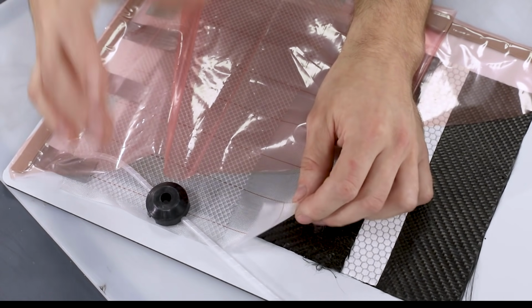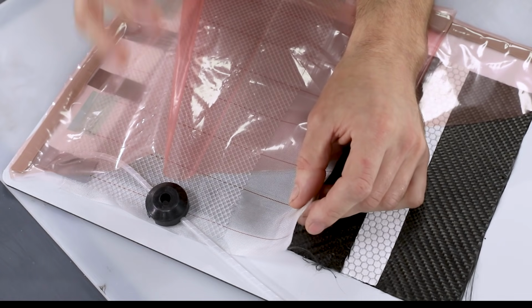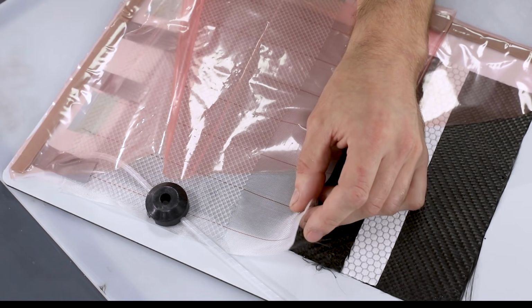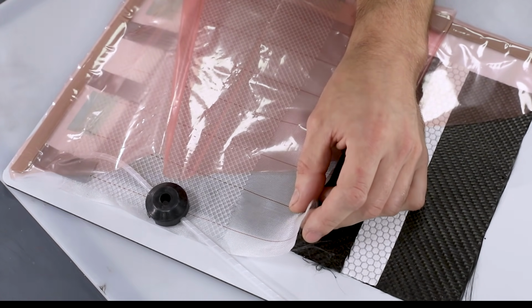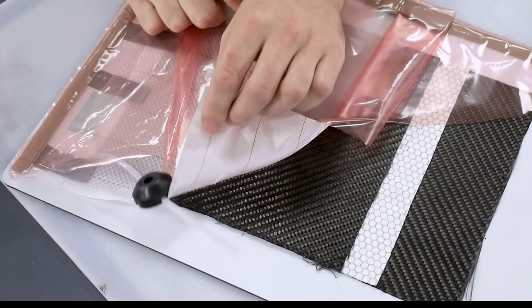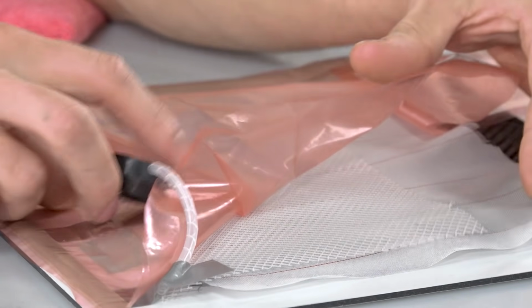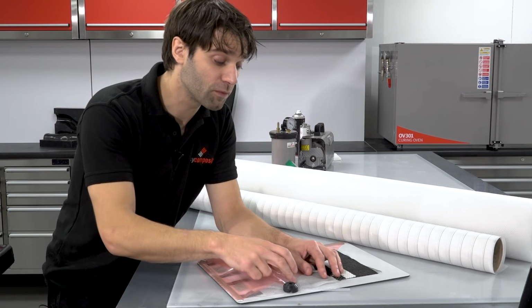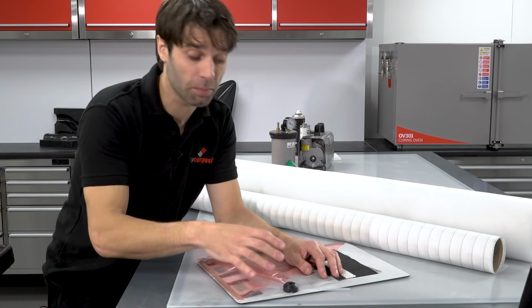The first layer is a peel ply. Now the purpose of a peel ply is to allow the resin to freely flow through it, but after the resin is cured, it can be peeled back and it will tear the rest of the consumables away from the part. Without this, the infusion mesh would stay permanently embedded in your part.